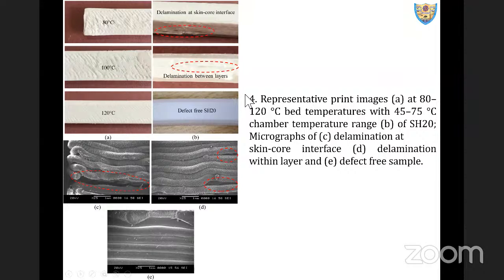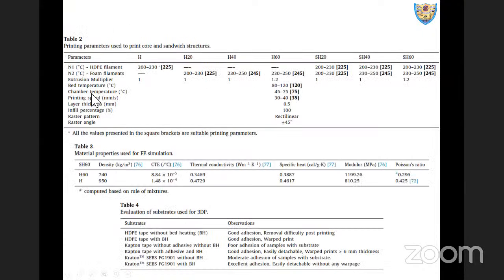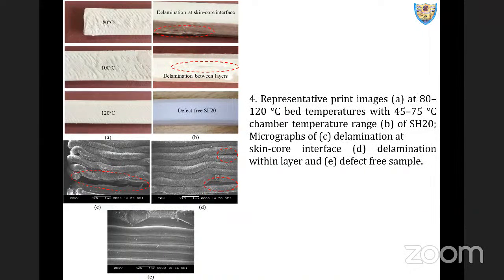So the adhesive bonding between the first layer of the print and the substrate depends, especially in 3D printing of polymers, on bed and chamber temperature. You can look around here. We have a bed temperature and we have a chamber temperature, the ranges which are found out to be suitable. So what figure 4a represents is a representative print image after peeling the samples. Peeling meaning removing the samples from the substrate at different bed and chamber temperature.